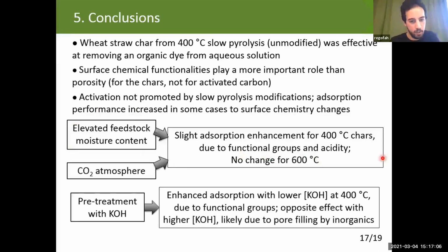And then for the KOH chars, there was better adsorption for the lower concentration of KOH at the lower char temperature, again due to functional groups and oxygen contributions, but the opposite effect with the higher KOH concentration, which was likely due to filling of the pores and the surface by inorganic materials.